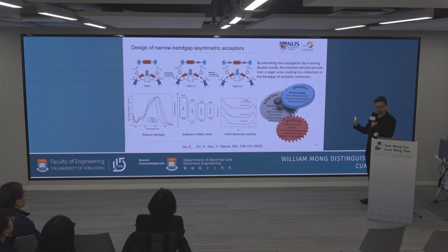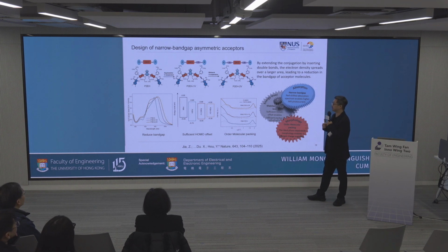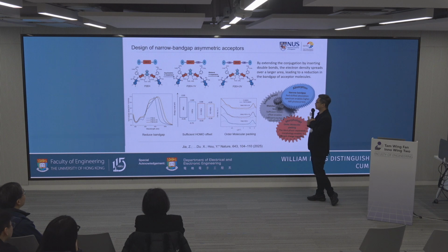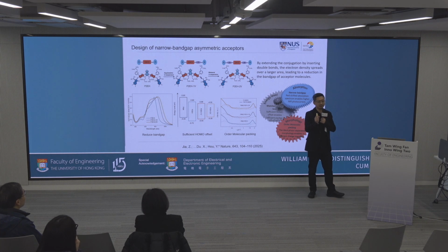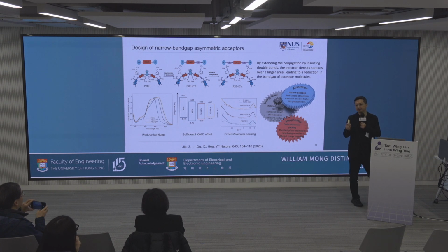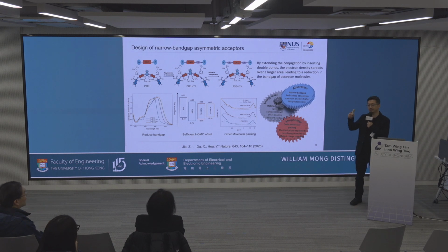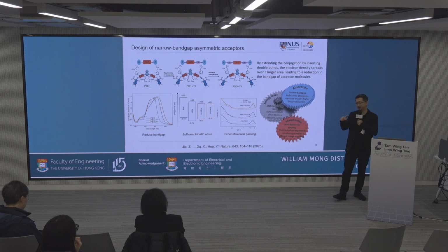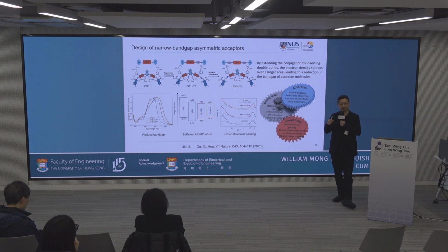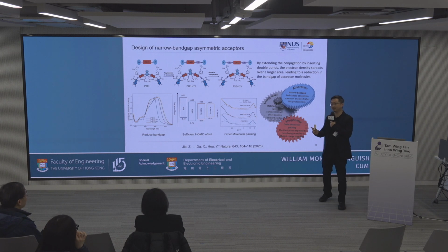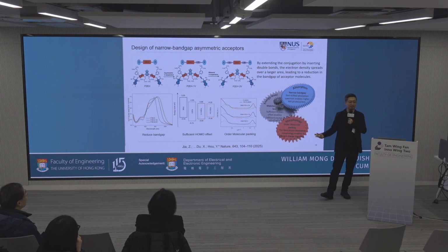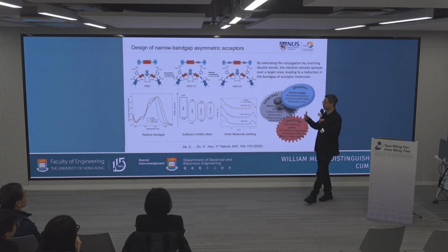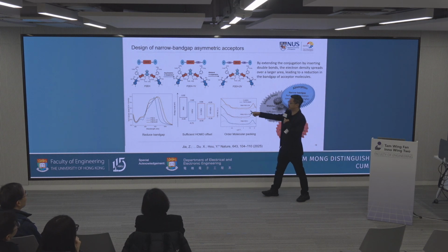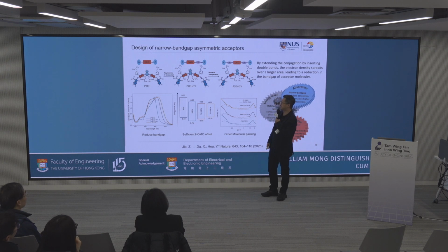And recently we also innovated this organic bottom cell, because the current organic bottom cell using Y6 has a band gap that is too wide. It's about 1.35 eV. If you look at the dual junction tandem SQ limit, the ideal band gap of the bottom cell should be around 1.0. Then you can really maximize the potential of the tandem. Otherwise, if the bottom cell band gap is too wide, you don't see much advantage from making the tandem. You can just use a single junction, it's enough. So therefore, we need to narrow the band gap of the OPV, and then the tandem starts to be more efficient and start to make sense.